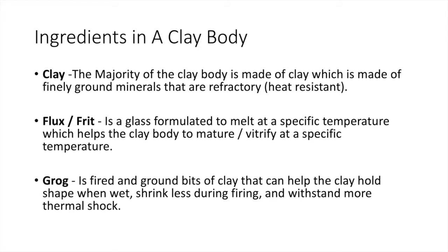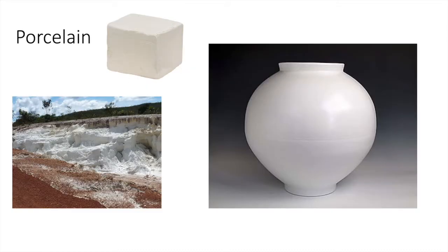So if that clay's already been fired, like the grog, it's not going to shrink, and it's going to make the clay shrink less, so less stress, less thermal shock in the firing, and also it's going to give it some body while you're building with it or throwing your pot. It's going to stand up and not be all squishy and fall over.